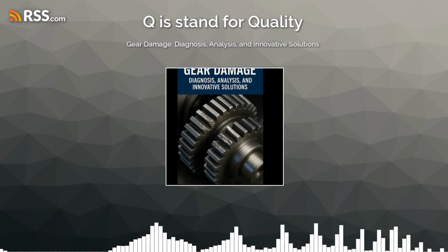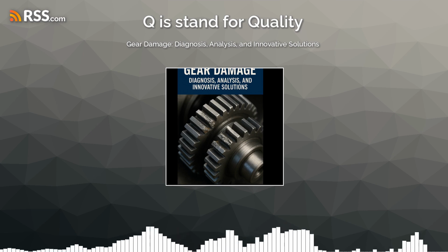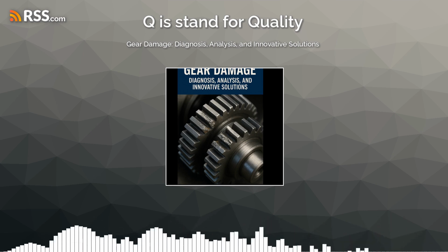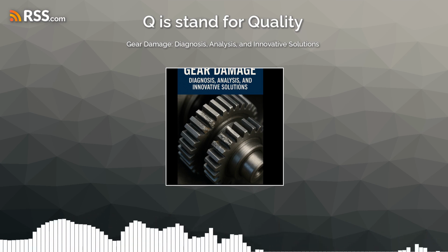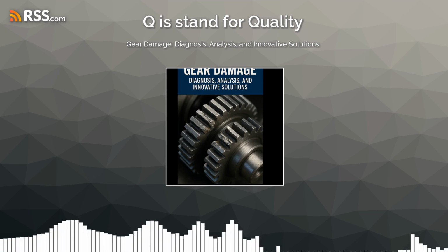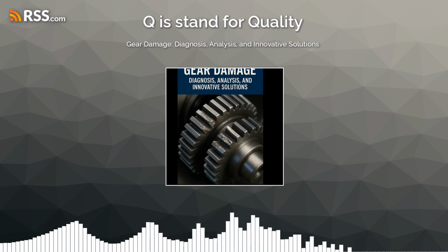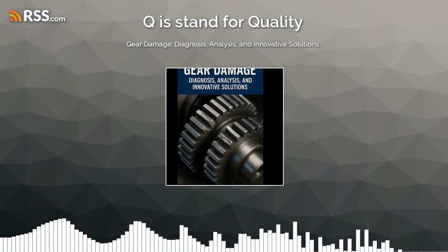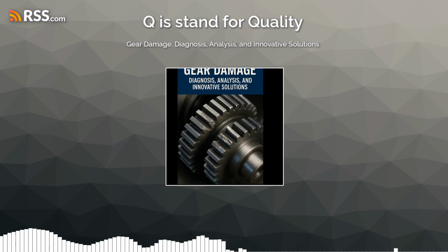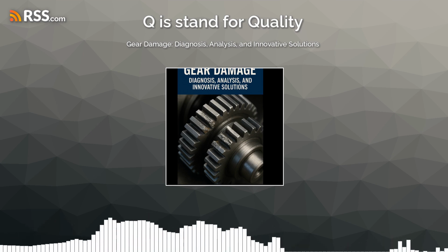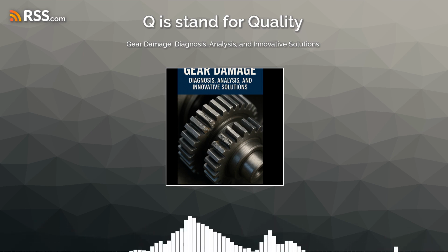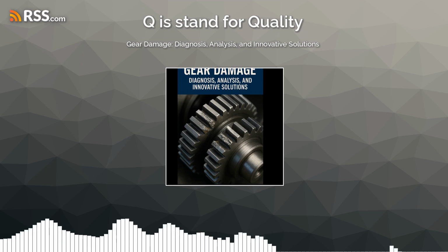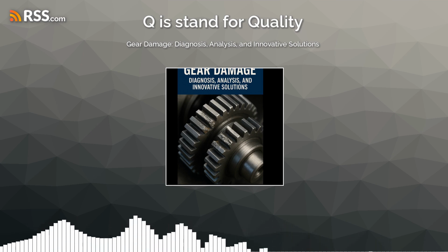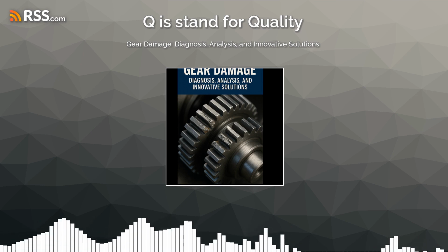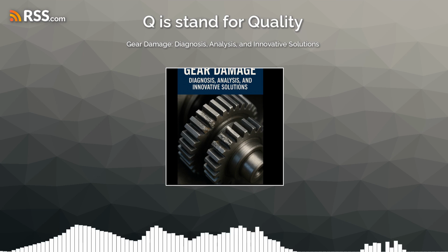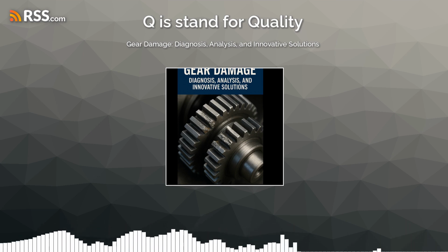So figuring out why a fracture happens sounds like real detective work. What factors influence it, and how hard is it to find the root cause? It is very much like forensic science for materials. The factors influencing fracture can span that entire life cycle we talked about, making root cause analysis pretty complex. Often it boils down to errors made way back. Faulty design choices, using the wrong material, defects introduced during production, mistakes during assembly, or even just improper operation or bad maintenance later on. What are some typical culprits? Things like increased bending stress, maybe from misalignment or overload, non-metallic inclusions in the material acting as weak points, defects from heat treatment messing up material properties, manufacturing flaws like surface scratches, and definitely excessive vibrations creating unexpected dynamic loads.